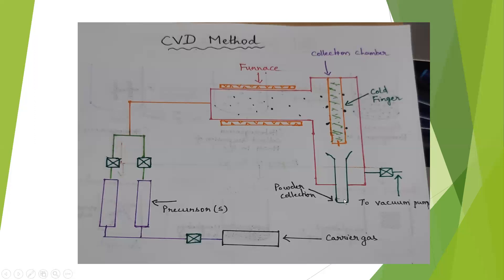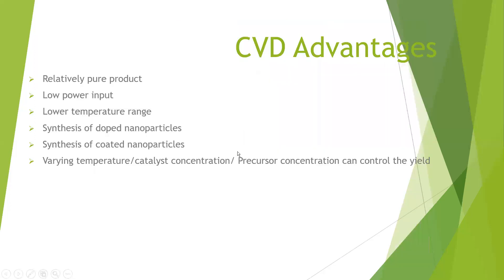To summarize the overall CVD process: metallo-organic compounds are used as precursors, the carrier gas is usually an inert gas, and the vapor stream is introduced into the furnace and then the vacuum chamber. Thermal decomposition of molecules takes place, forming small particles. These small particles condense on the liquid nitrogen-cooled rotating substrate — the cold finger — and the powder is scraped off and sent for further analysis.